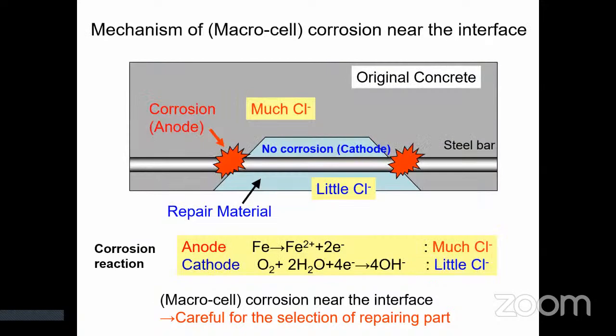This slide shows the mechanism of macrocell corrosion near the interface after cross-sectional repair. Corrosion reaction consists of an anodic reaction and a cathodic reaction. In the repair material, the cathodic reaction occurs because there is little chloride ion in the concrete. On the other hand, the anodic reaction occurs in the original concrete with high chloride ion content near the interface. Therefore, macrocell corrosion occurred near the interface. Also, this figure indicates we have to be careful in the selection of the repairing part.